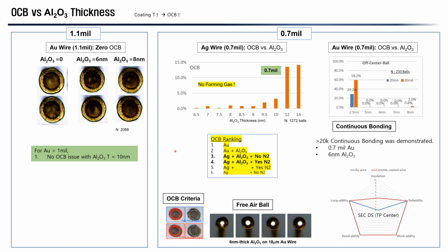After we've done many testings, we came up with an OCB ranking. Number 1, conventional gold wire. Number 2, gold wire with aluminum oxide coating. This is very interesting. Number 3, silver wire with aluminum oxide coating, but no forming gas. No forming gas is better for the silver wire than forming gas.